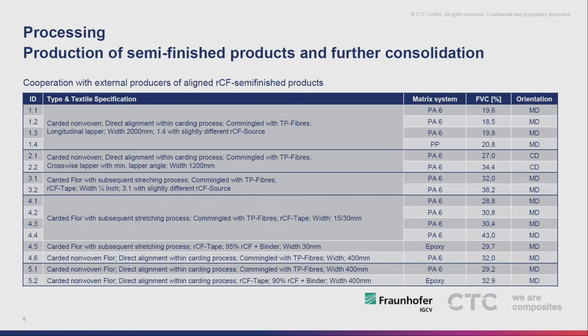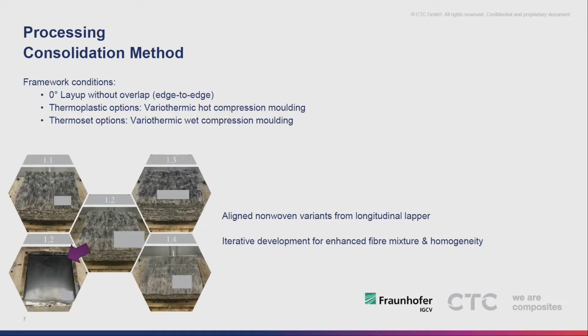We always assess the machine direction of production, because basically if you pull a yarn or a non-woven through such a process, you never get a perfect UD. You always have some fibers lying not in the perfect UD direction, some fibers lying basically at 90 degrees to that. And the practical approach was pretty simple. We got all these materials. We processed them into flat plates. Alignment was manually placed for all of these technologies, since we work with very small size coupons and very small batch quantities of material.